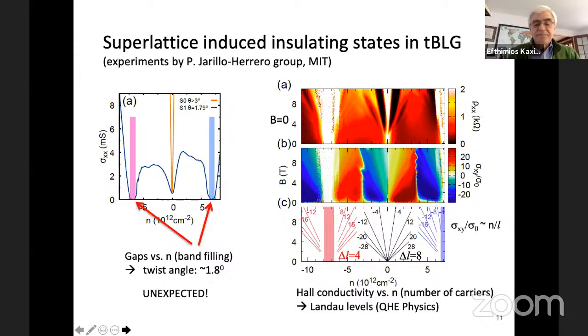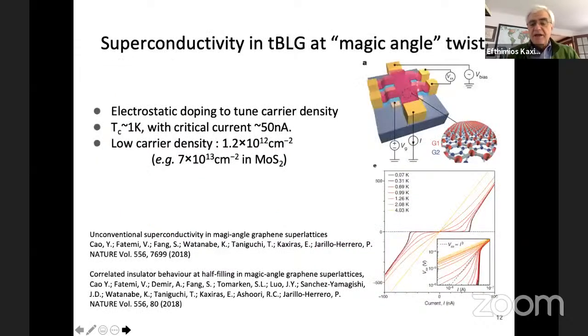Okay, so indeed you can observe in this type of twisted layer this interesting behavior, but you can actually observe even more interesting behavior. This was a big surprise and discovery a couple of years ago, by the group of Pablo Jarillo-Herrero at MIT and his collaborators. And what they did is they put such a bilayer graphene system, two layers of graphene shown here. The one on the bottom is highlighted in blue, the one on the top is highlighted in red.